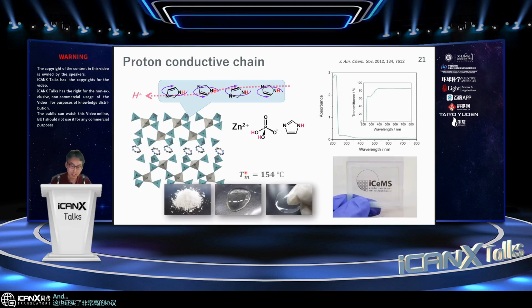And in this case, it's the same as the previous example. This crystal melts, in this case at just 154 degrees C, and we can also get this transparent melt and it forms the glass.